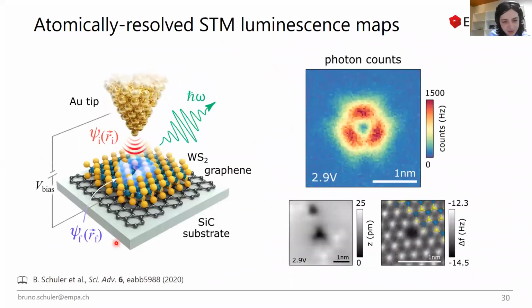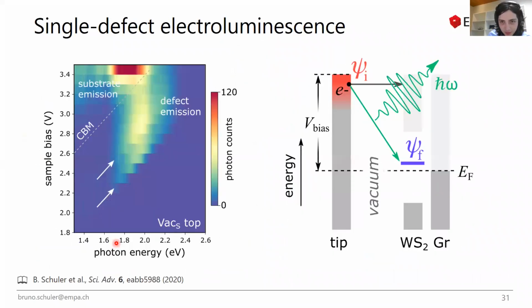Okay, that's an interesting question. So we tried. The problem is if you just look at the counts. We are working on a substrate which is not plasmonic. It's graphene on silicon carbide. So the count rates that we get are just very small to do a G2 measurement. So we tried to set it up, but then the photon statistics were not enough to do a convincing G2 measurement.